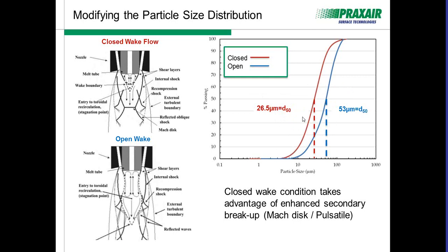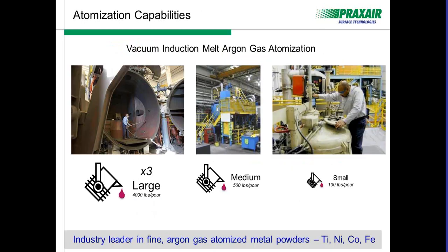When we look at that distribution, our average is at 26 microns and our standard deviation is very tight. In the open wake, we create coarser particles. Those are some interesting terminologies to understand. What we're developing and understanding is that if we use a close-coupled process and a closed wake gas structure, we can create some of the finest powders with the tightest standard deviation, therefore maximizing our yield of powders within the range that our customers require for additive manufacturing.